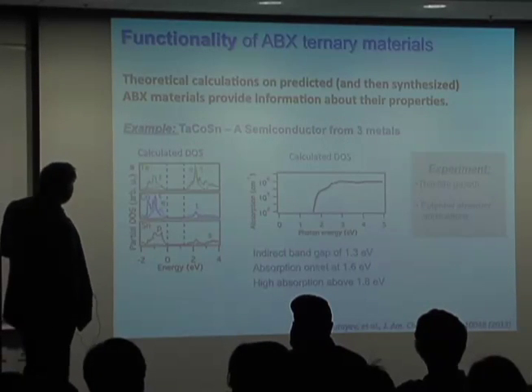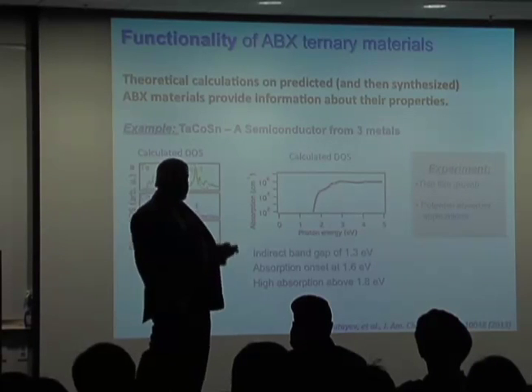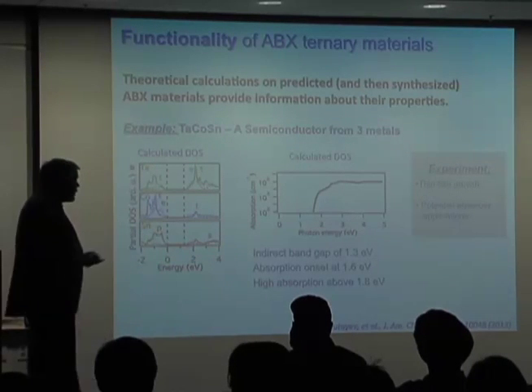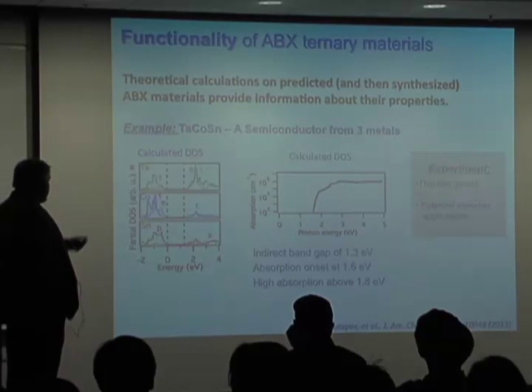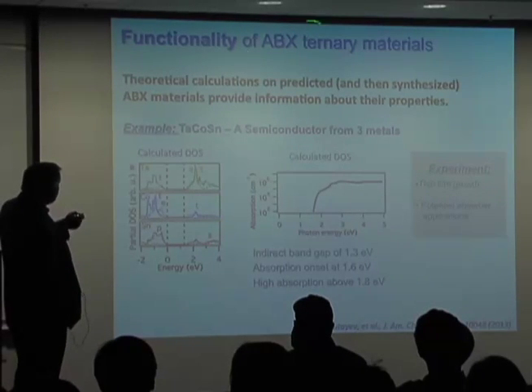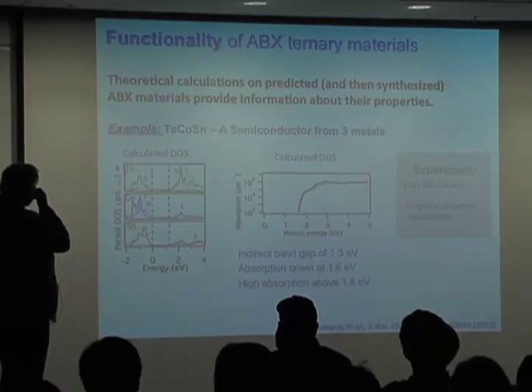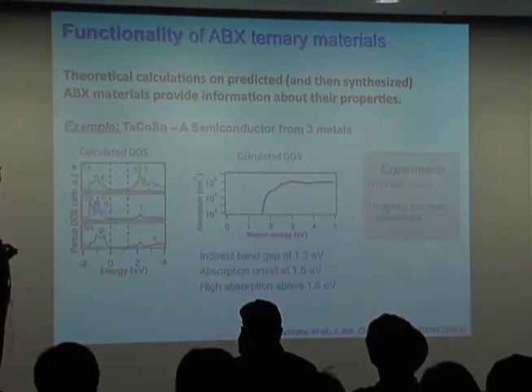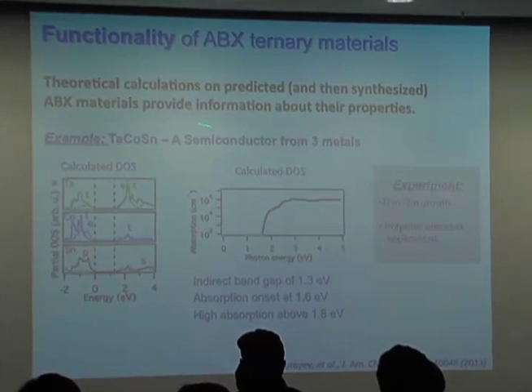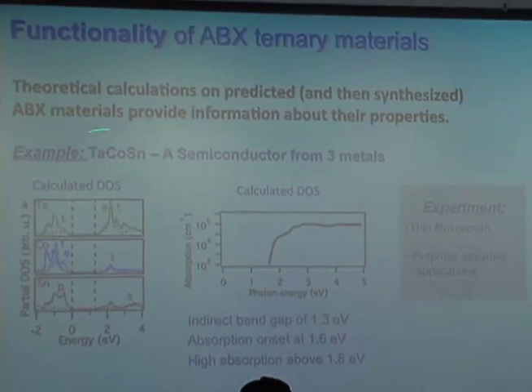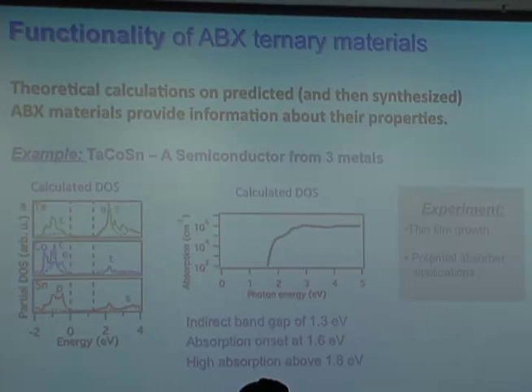We want to go the next step and say we don't just want to make materials that haven't been made before. There ought to be a real reason for it, and of course functionality is our reason. So now let's take another look at this ABX system, and start doing some calculations on functionality. Here's one, tantalum, cobalt, tin. Three metals combine in an ABX and make a semiconductor. We calculate an indirect gap at 1.3 eV for this material, an absorption onset at 1.6, and high absorption above 1.8 eV. And in fact, if we look at the calculated densities of states, we can calculate those absorptions.